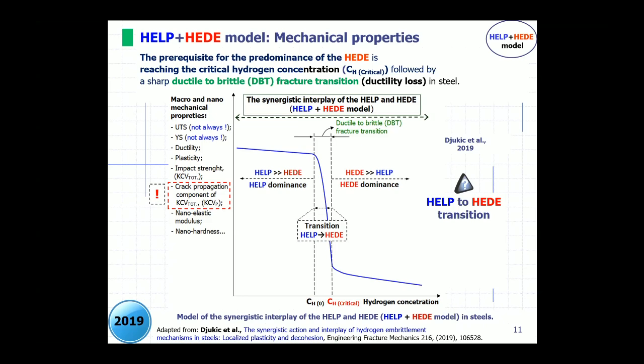This is the case of high strength metallic materials. In the case of more ductile material, we have a not so sharp drop in ductility and fracture toughness of the material, but this is very dangerous from a structural integrity point of view, because at some critical hydrogen concentration we have a full brittleness of the material, which means that the material will lose its ductility as a result of HEDE mechanism predominance.